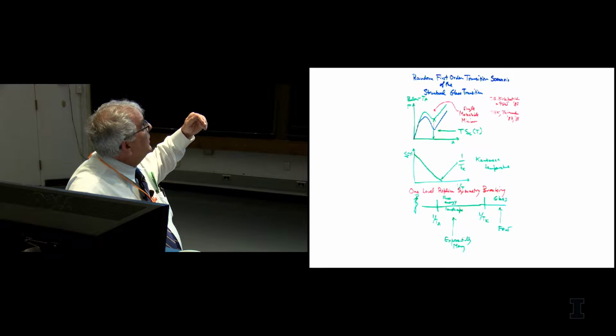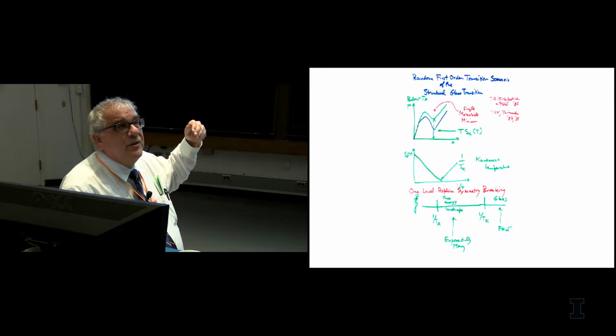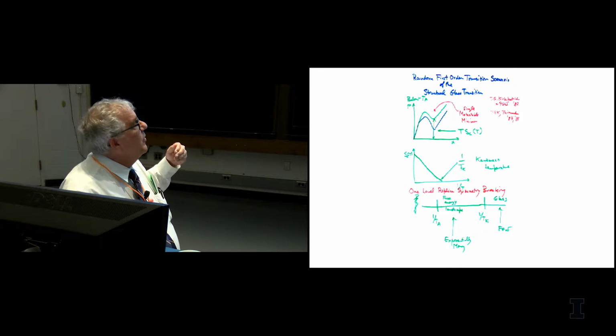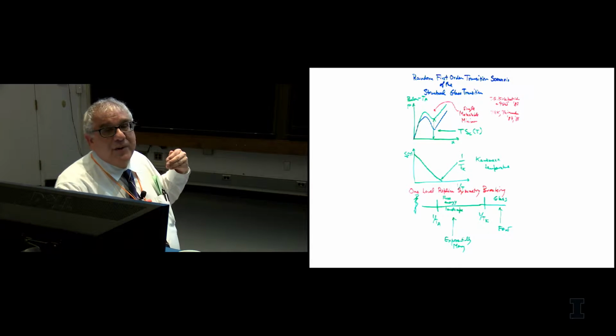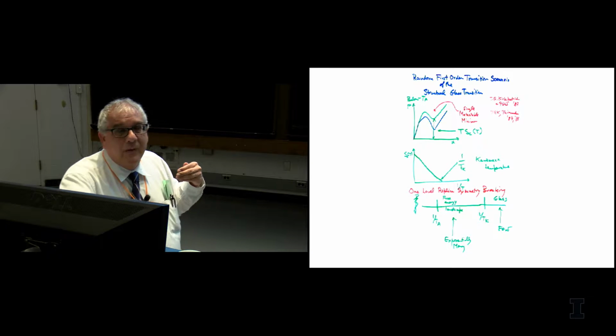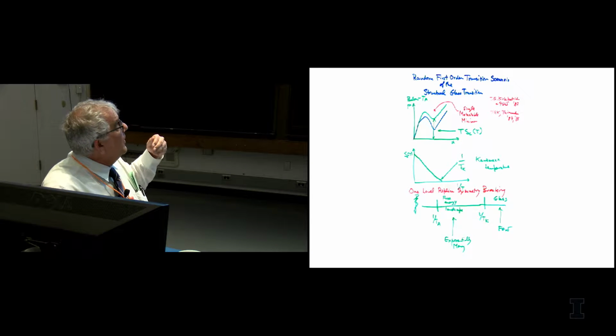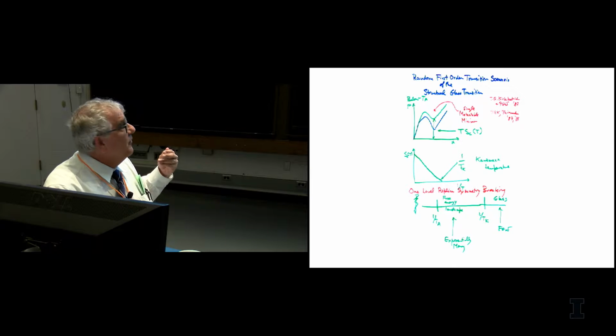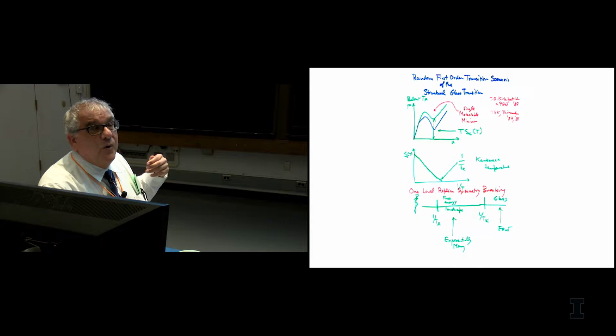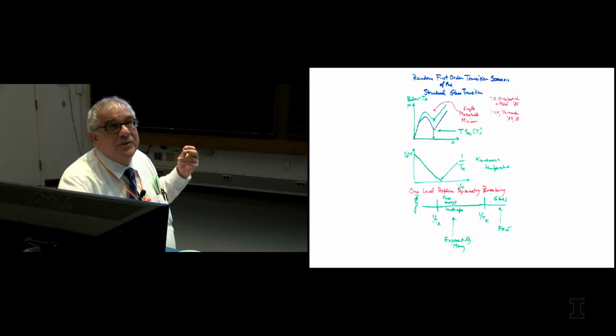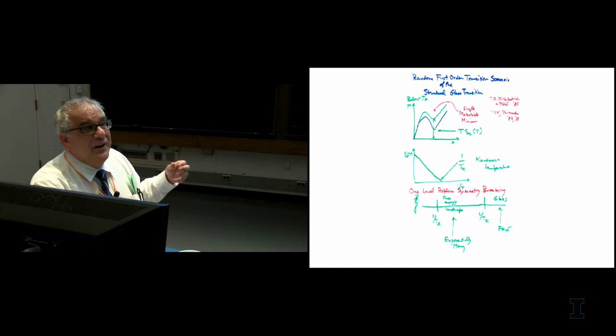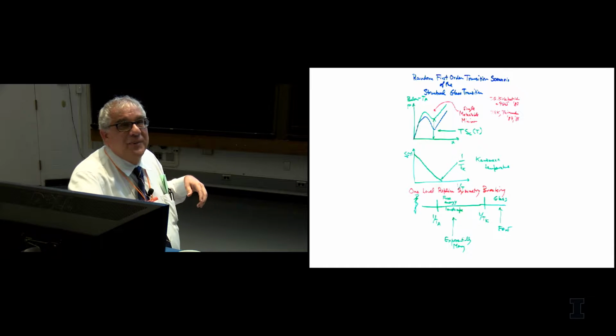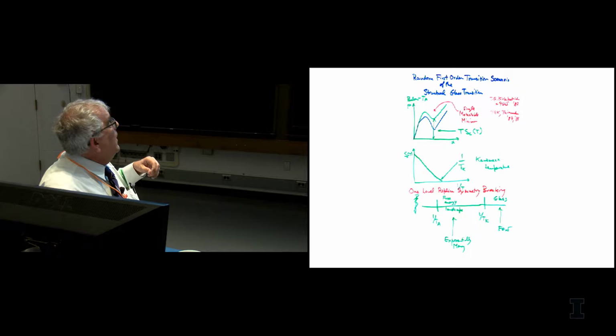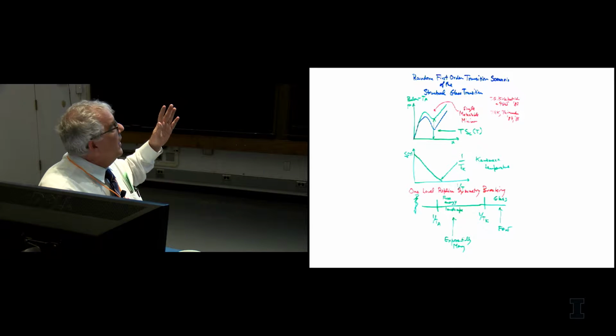And what's happening is that this metastable minimum, there isn't a single one. There's actually many states in which you can be trapped. There's a thermodynamically large number of them. And this thermodynamically large number is reflected in what's called the configurational entropy. This is a quantity that can be determined by calorimetry, basically by measuring the heat capacity and subtracting off the heat capacity of vibrations. There's, of course, some debates exactly how you do that.